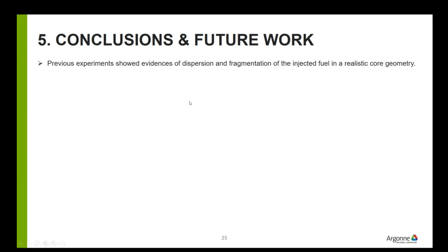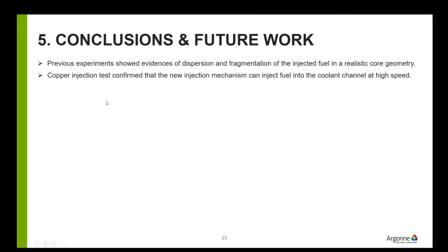Our previous experiments, the single pin relocation experiment and the pin bundle relocation experiment without pressure injection, showed some evidence of dispersion and fragmentation of the injected fuel in a realistic core geometry, not in an open pool sodium geometry. Then we conducted a copper injection test, which confirmed that the new injection mechanism of the new pressure vessel can inject fuel into the coolant channel at high speed because of the pressure difference.